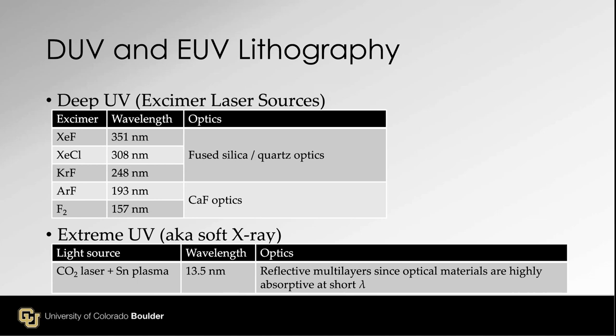But people want to have gate length smaller than 10 nanometers, so those guys are too large. So now the semiconductor industry is looking at extreme UV, also known as soft X-ray, because it's getting close to the X-ray region. The wavelength of this particular light source, a CO2 laser with a tin plasma, is 13.5 nanometers. Okay. Small, good. But there are some practical issues associated with that as the wavelength goes down.